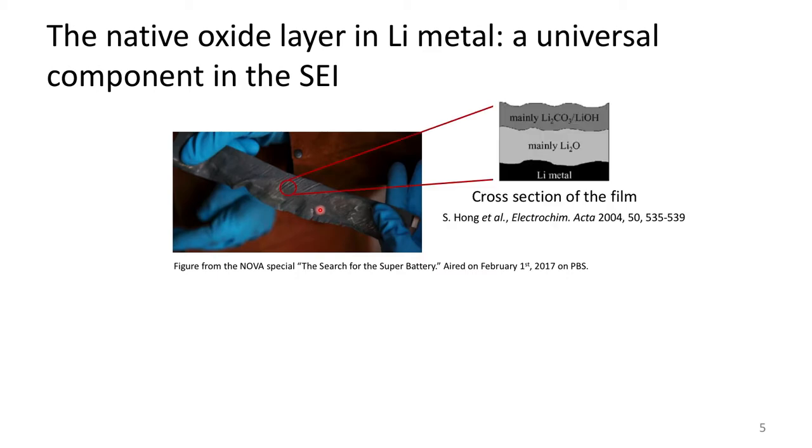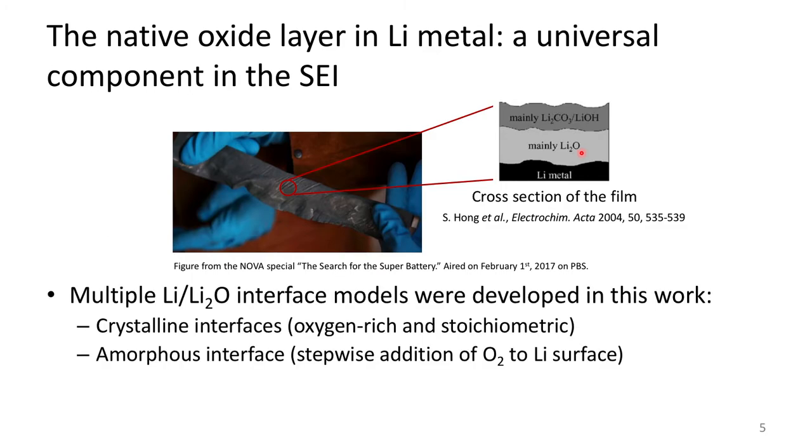Some past studies have assessed the composition of the native oxide layer using X-ray photoelectron spectroscopy, or XPS, and have all generally agreed that there's a layer of lithium oxide, or Li2O, in direct contact with lithium metal. So in my work, I wanted to model this lithium-lithium oxide interface using DFT.